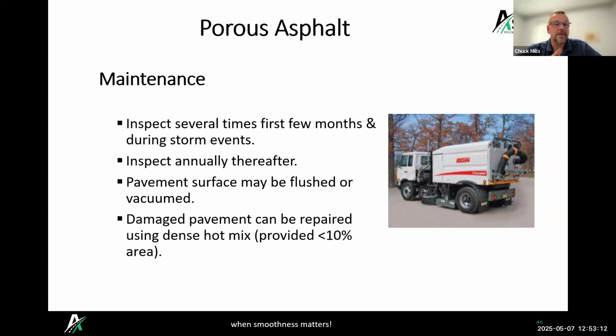The pavement surface may be flushed or vacuumed. Most people have found that running a street sweeper and backing it out once or twice a year seems to be working pretty good. And any damaged pavement can be repaired with regular hot mix, as long as you're not closing off more than 10% of that infiltration area.